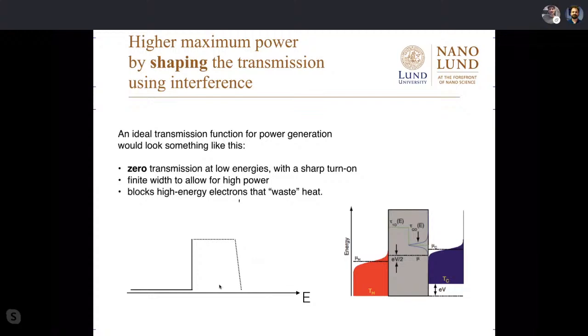You can actually play with this a little bit. So these were the transmission resonances you get for free. You can also dream of what your transmission resonances would be if you could choose. And it turns out if you want to build your own transmission function, you would want to build one that basically blocks electrons at low energies to zero and has a very sharp turn on. That's important. And then you want to have a finite width to get power. But what that shape then looks like turns out to be less important. So you could have a square shape or some kind of tail or something. The important bit is this sharp turn on from zero to high quickly.